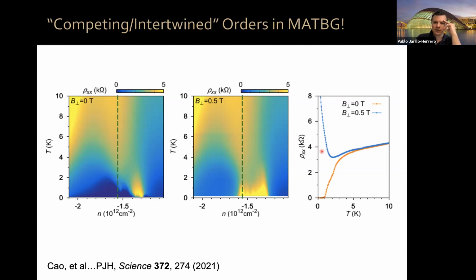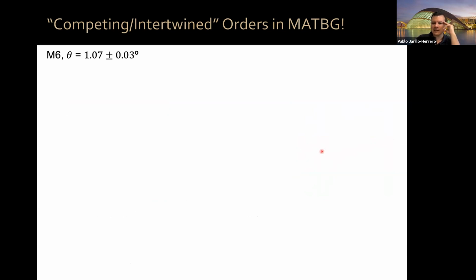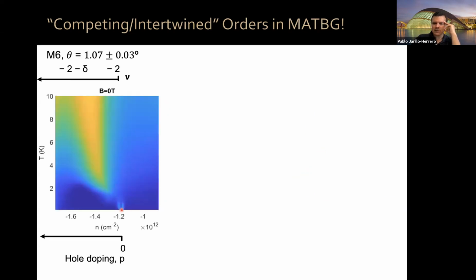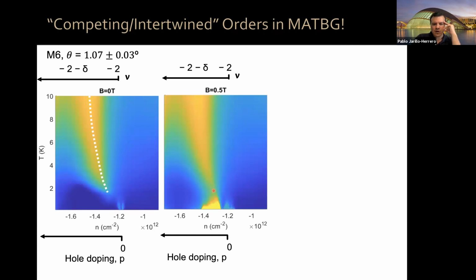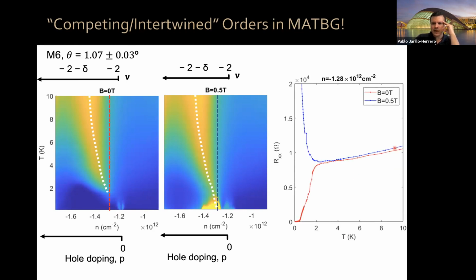Right, so we saw this in one device. We thought, okay, let's see if we see it again. And these are data from another device, 1.07 degrees in this case. In this case, the correlated insulator state is barely visible, just a tiny feature here. And we have this banana, this resistance ridge, which happens there and creates a depletion in the superconducting dome. If we now apply a small perpendicular magnetic field, we can see that this resistance ridge connects to an insulating state at low temperatures, which is clearly separated from the correlated insulator state that occurs at 2 holes per moiré unit cell. And again, if you measure your resistivity there versus temperature under both conditions, in one case you have a transition to a superconducting state. In the other case, you have a transition to an insulating state.